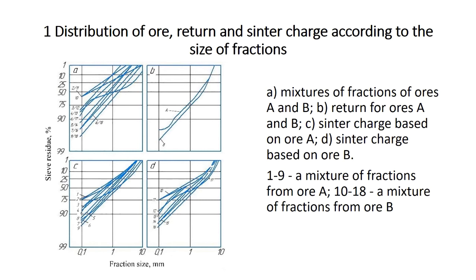The oxidation state of the return in individual experiments also fluctuated. It was determined by calculation. When using ore A, it was 94%, when using ore B 97.3%. Thus, the dependence of the oxidation state of the return on the oxidation state of the charge is visible. The return flow rate of 40 kg per 100 kg of ore mixture was kept constant.